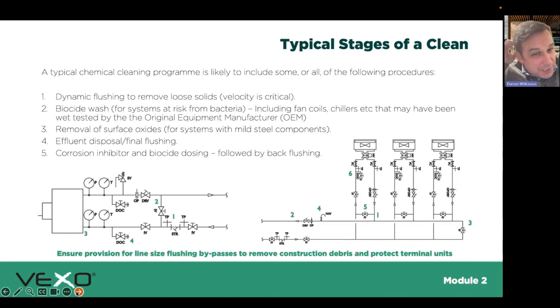Typically biocide washes for systems at risk from bacteria. If you've got terminal units that are being wet tested, or even chillers that are wet tested, it's a really important question to ask the OEM. Because I found a chiller once many years ago, before we opened it to the main system, and this is before we were in the world of making biocide washing a regular thing, we found about 4 inches of biofilm inside the chiller where it had been wet tested and sat on a dock somewhere for probably months.